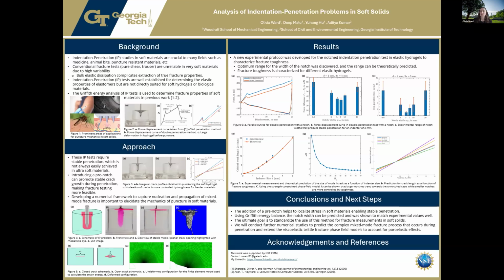Indentation and penetration of soft materials are important in many real-world applications, including medical procedures, understanding animal bites, and designing puncture-resistant materials. However, measuring fracture properties in these materials is particularly challenging. Traditional fracture tests, such as pure shear or trouser tear tests, often fail for very soft materials like hydrogels, because these materials undergo large deformations and significant energy dissipation, which makes it difficult to isolate the true fracture toughness of the material.